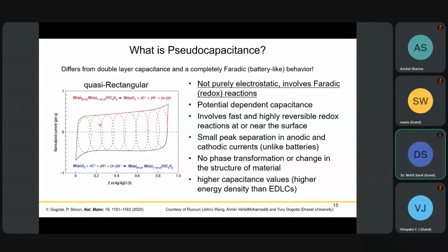For example, in ruthenium oxide, which was the first studied material here, redox happened at each potential. When you sum it up, it looks like a rectangle, but actually it is not so. It is not purely electrostatic. The charge transfer takes place on the surface, so we call it a Faradaic redox reaction that happens on the surface.